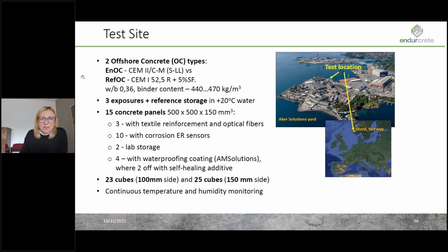Maybe just a small note: the reference concrete was a little bit unfair, I think, to the EnDurCrete concrete, but we can discuss it later. The water binder ratio was also very low, 0.36, with relatively high binder content. As for the exposure zones, we could say there are actually 4 exposure zones. We have 3 marine exposure zones, XS1, XS2, XS3, and additionally frost, where in the coldest months the temperature goes down to -8 degrees.